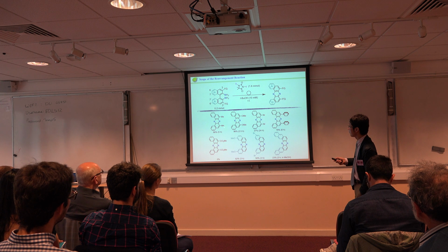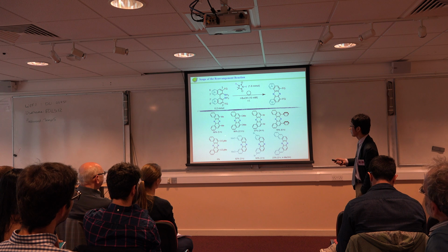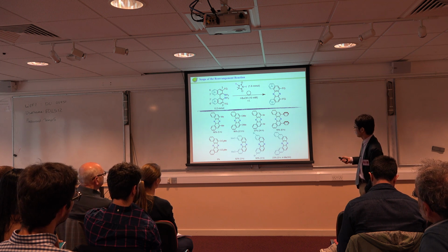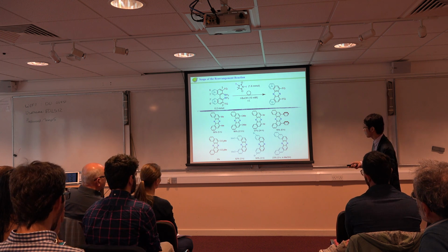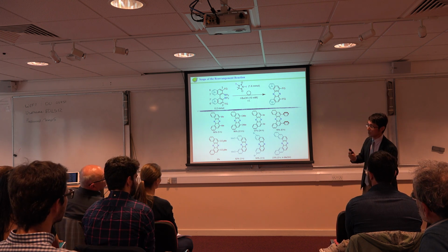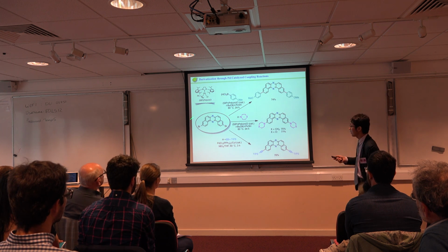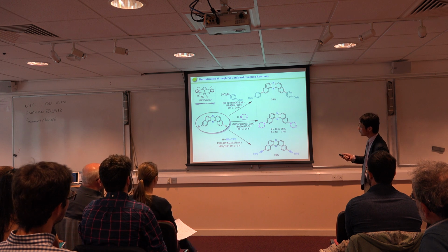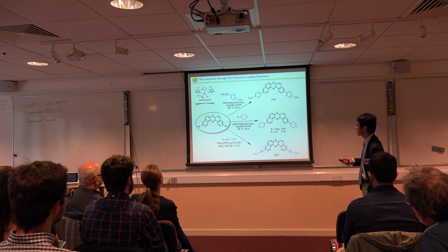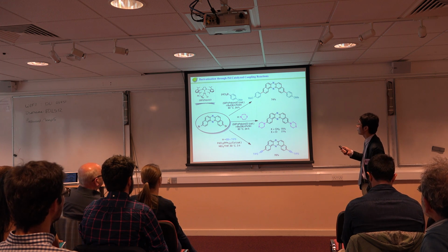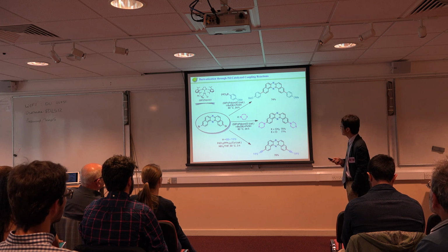As you can see, you can introduce a dibromo substrate here, and also here, and you can prepare U-shaped highly conjugated systems that cannot be accessed by conventional methods. We also demonstrated that this dibromo compound can be utilized for access to functionalized dibenzo compounds by palladium-catalyzed reactions.